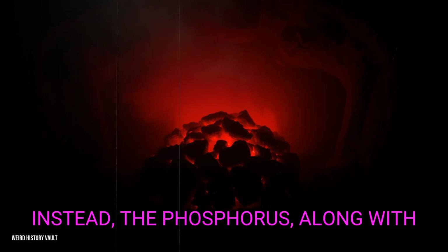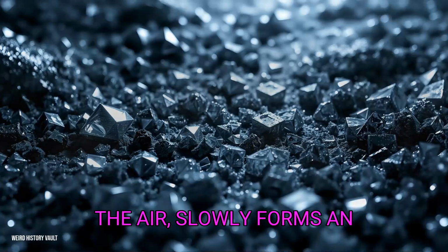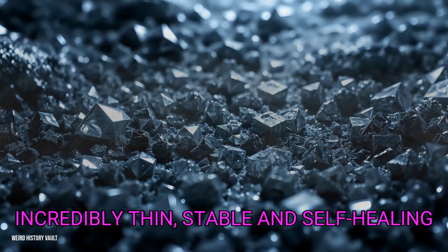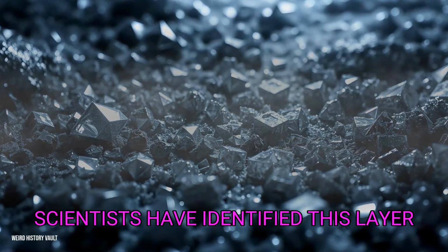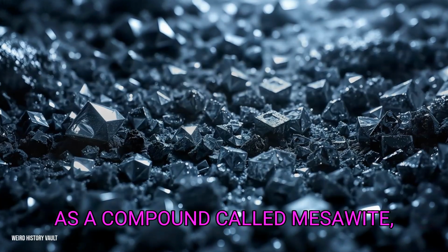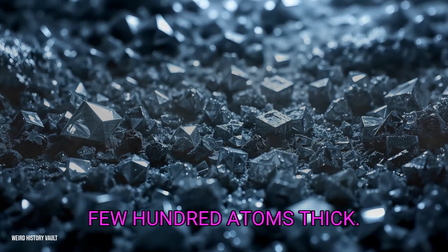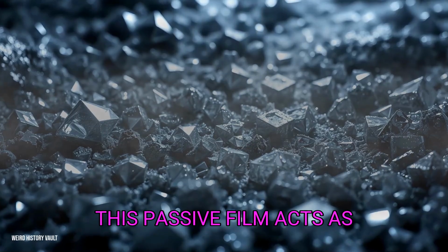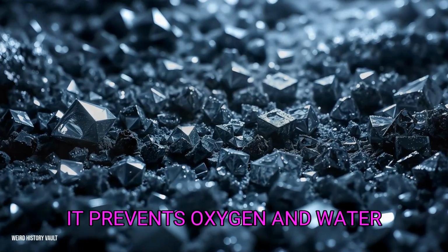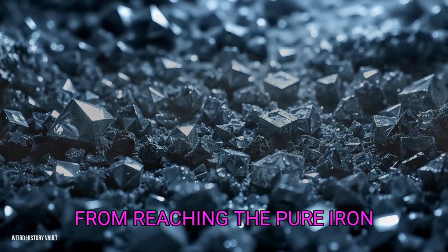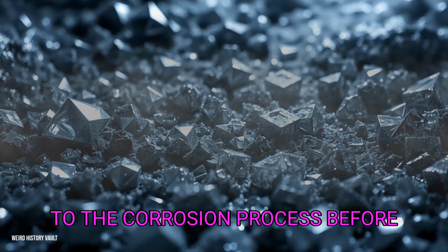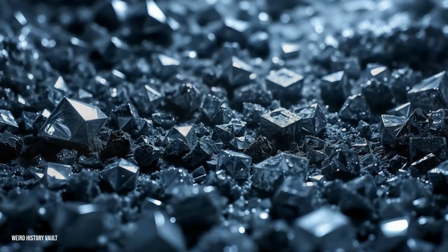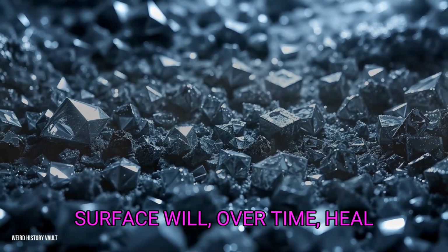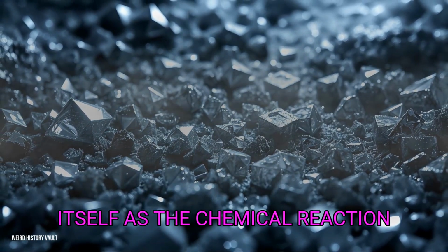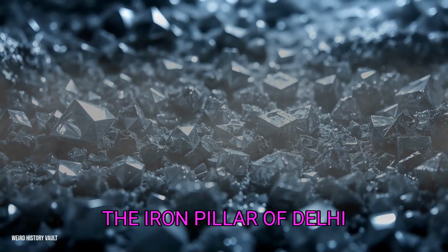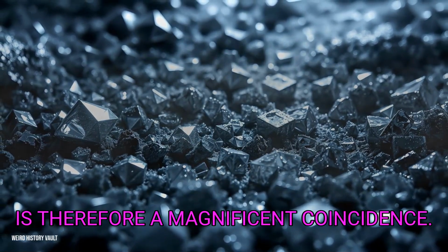Instead, the phosphorus, along with the iron and oxygen from the air, slowly forms an incredibly thin, stable, and self-healing protective layer. Scientists have identified this layer as a compound called misawite, a crystalline skin only a few hundred atoms thick. This passive film acts as an impenetrable shield. It prevents oxygen and water from reaching the pure iron beneath, effectively putting a stop to the corrosion process before it can truly begin. Any small scratch on this surface will, over time, heal itself as the chemical reaction forms a new protective layer. The iron pillar of Delhi is therefore a magnificent coincidence.